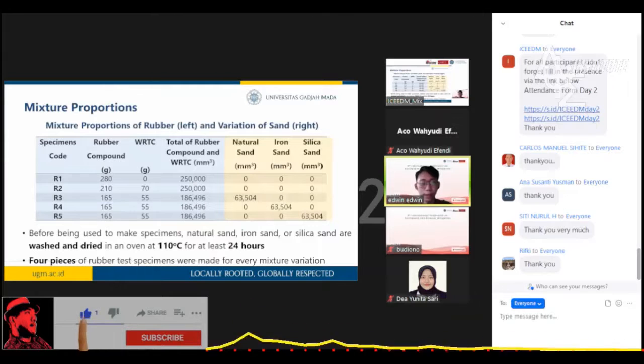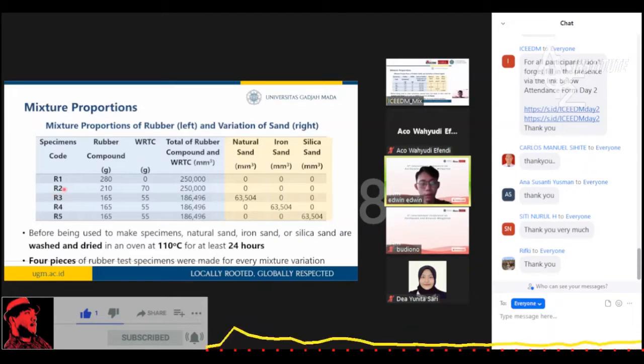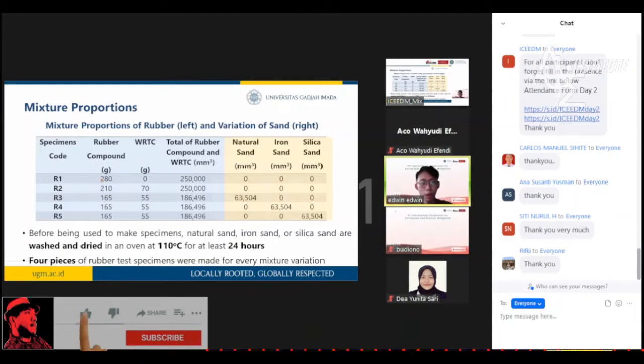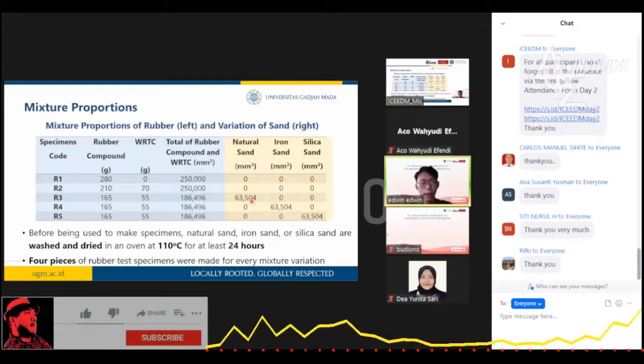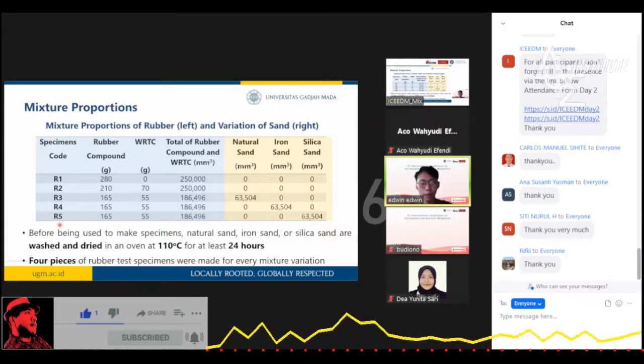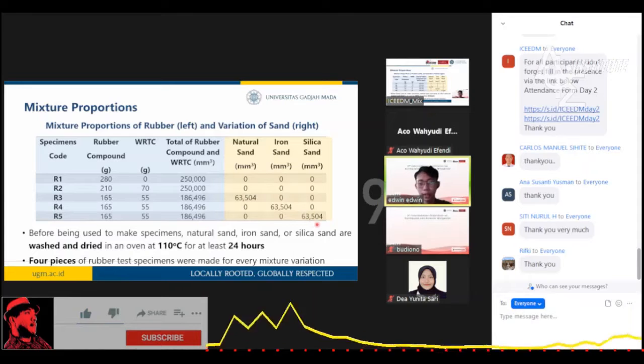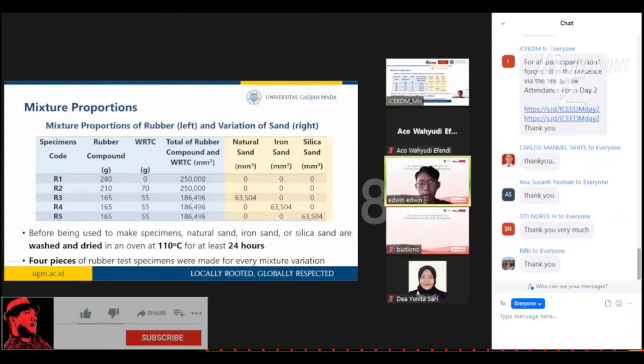And there were 5 mixture variations used in this research, as we can see in the table. R1 or specimen made from rubber compound only, and then R2 or specimen made from mixture of rubber compound with 25% WRTC, and then R3 or specimen R2 with compacted natural sand, and then R4 or specimen R2 with compacted iron sand, and lastly R5 or specimen R2 with compacted silica sand. The one highlighted in blue color is proportions for rubber compound and WRTC, and the one that is highlighted in yellow color is proportions for sand.